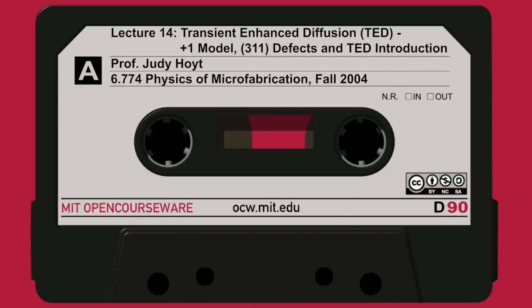Pre-amorphization also has another advantage if you want to think about it. Remember we were talking about ion implantation a few lectures ago. We were talking about ion channeling and the fact that ions can be knocked into these channels. Because you have a perfect crystal, they can go a long ways before they stop. And this creates these long tails, which makes it very hard to get an abrupt, shallow junction. Well, if you amorphize the top 3,000 angstroms prior to putting the boron in, that eliminates the possibility of ion channeling in those top 3,000 angstroms. There is no crystal. It's not single crystal.